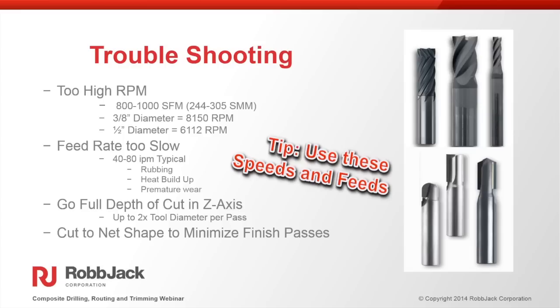So on troubleshooting, what tools should I pick? What things can I use for the application on trimming? Most of the time, people are going too high of an RPM. So RPM range depends on the material and how much engagement you have. But worst case scenario, we'll see tools doing full slots, we can run that 800 to 1,000 surface footage. That's a pretty good range. So for a 3/8 tool, 8,150 RPM to 10,000 RPM, and then the 1/2-inch tool is around 6,100 RPM, which is typically a lot slower than we see people using the tools. But in our testing and research, you get the longest life, and you really get rid of that abrasive wear out of the tool when run at these speeds and feeds.